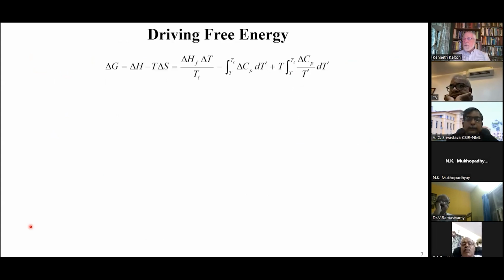Now, one of the key factors you need is the driving free energy. You would actually have to calculate it knowing the enthalpy and the differences in specific heat between the liquid and the crystal phase, but often those are not known. So often what's done is to use just the leading term and assume that delta Cp is effectively zero. This is sometimes called the Turnbull approximation.